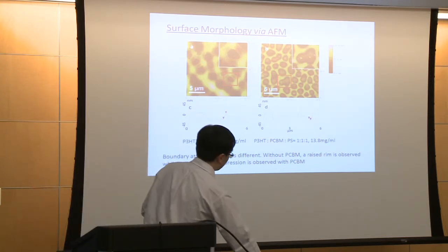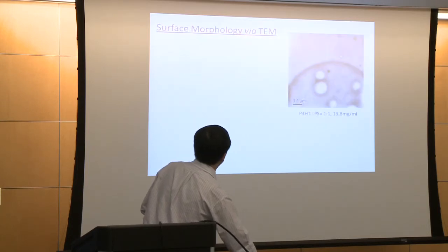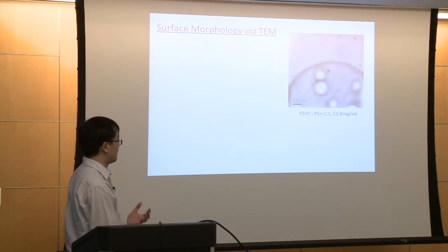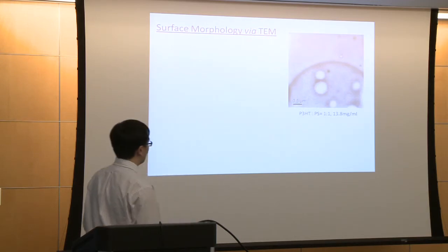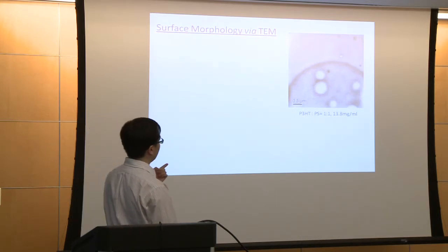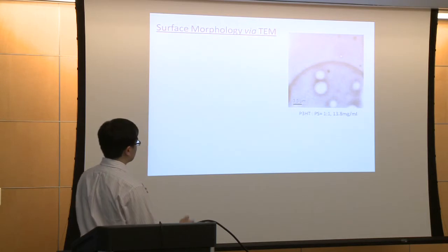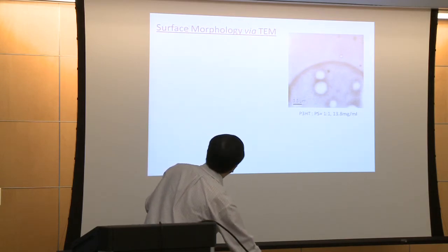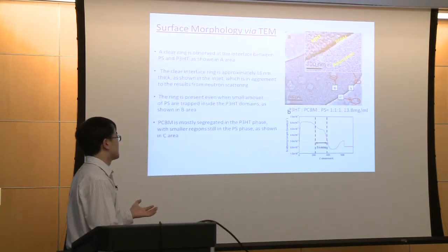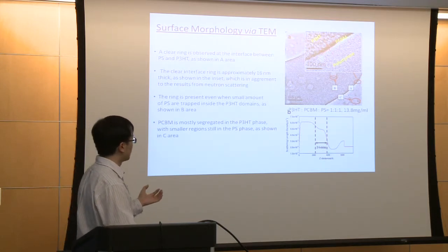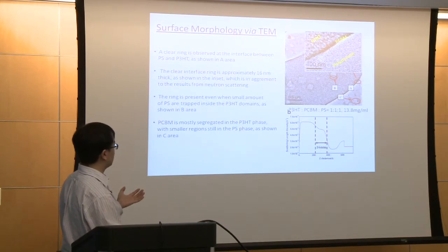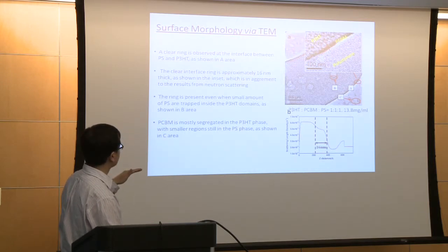But in order to further confirm the segregation, we use the TEM to help us determine whether the PCBM are really segregated at the interface. So this is the TEM image for the sample without PCBM. That's just P3HT and the polystyrene. You can focus on the boundary of the domain. You can see although there's some boundary there, it's not that clear. However, after we introduce PCBM into the system and observe under the TEM, you can see a very significant dark line along the boundary, right?